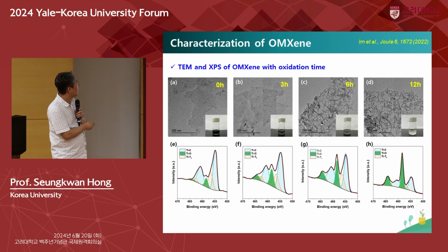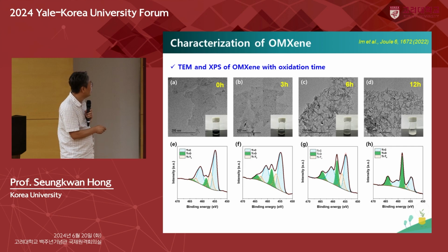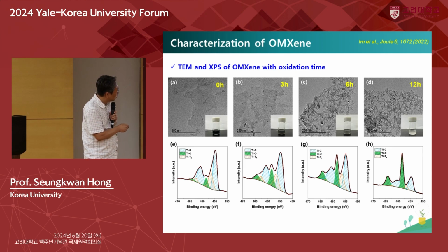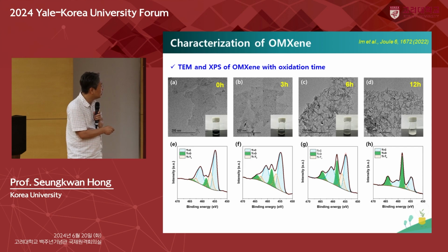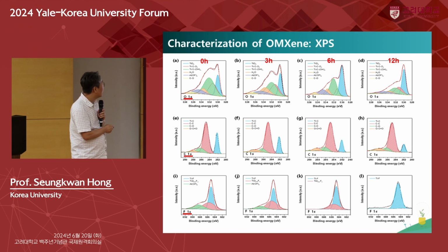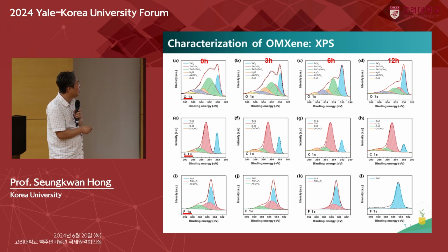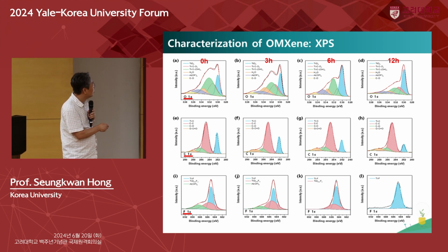So this is the characterization of O-MXene. Through the oxidation, this is the TEM imaging, and this is the XPS. So the surface is partially oxidized, and finally, through the full oxidation, it is wrapped and then changes like this one. The color also changes from black to white. This confirms the oxidation of the MXene layer. This is the XPS, the oxygen and the carbon and the fluorine. You can easily follow that the titanium oxide layer is gradually formed. This is the blue one.